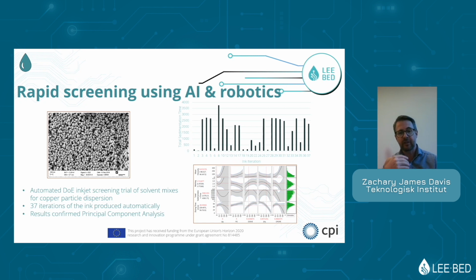Once you have that solvent-particle compatibility map, you can then use that to make the ink. So we're using this sort of AI or design of experiments, measuring on different solvents, mixing the solvents, and then measuring the particle dispersion, and then using that in order to make the inks.